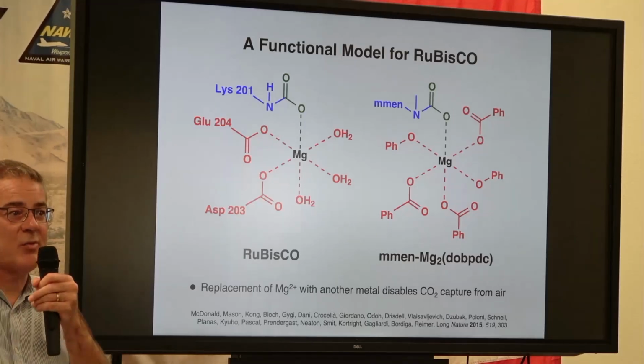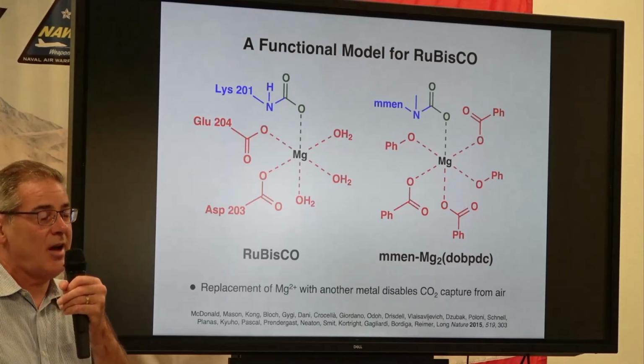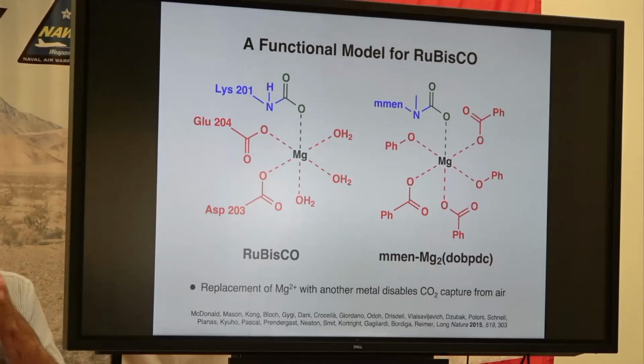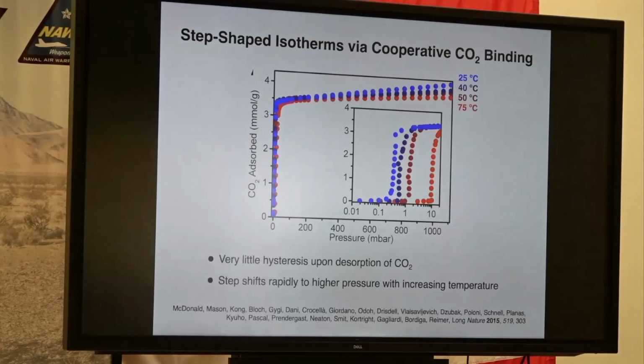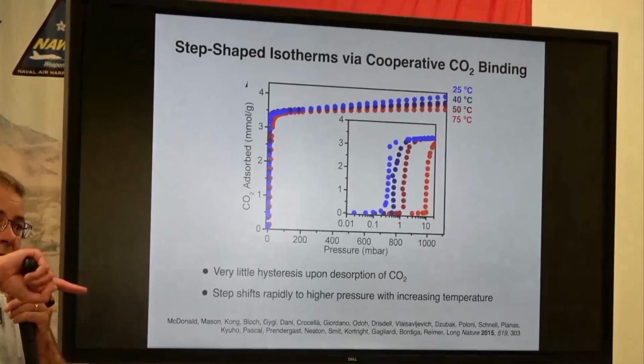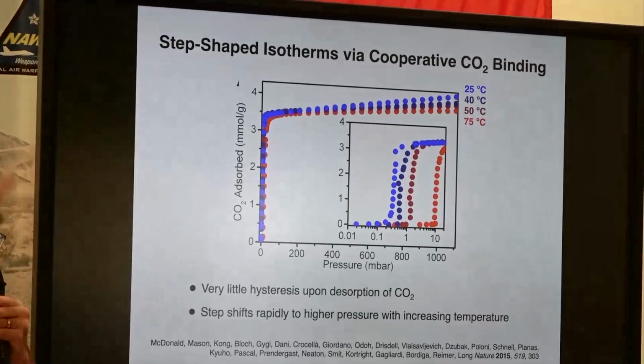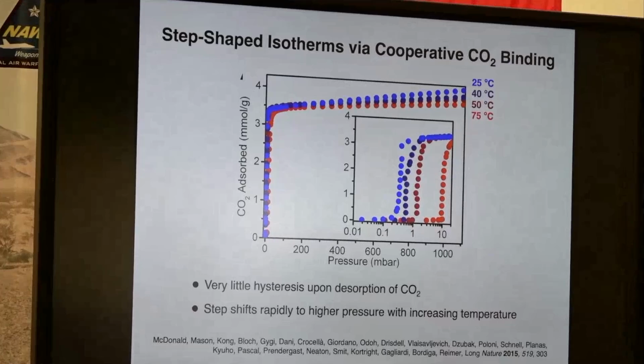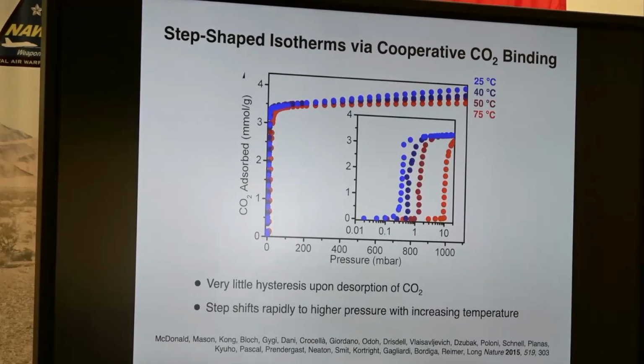But this has something that Rubisco does not. Rubisco does not bind CO2 cooperatively. It turns out the MOF does. So if you look at the very low pressure region of these adsorption isotherms, for the first time, we have a material that doesn't have a Langmuir response to CO2 under these conditions. These are sharp, step-shaped isotherms, and nobody had ever seen that. And it took us quite a while to figure out exactly how it was working, but I'll show you the results. If you model these steps with the Hill equation that I showed, you get n equals 11.